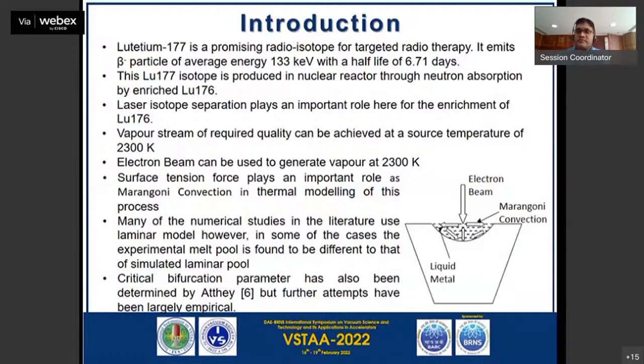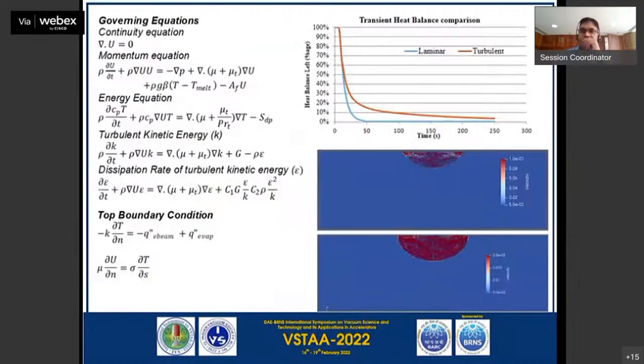Many numerical studies have been carried out in the literature, but mostly they have considered a laminar model. In some cases, they matched the post-solidification pool width and pool size, but found a considerable difference. To explain that difference, they went for turbulence modeling, through which they increased the effective momentum and thermal diffusivity.